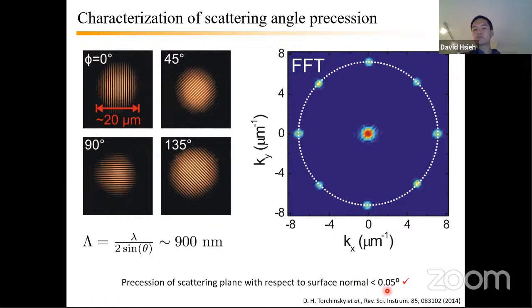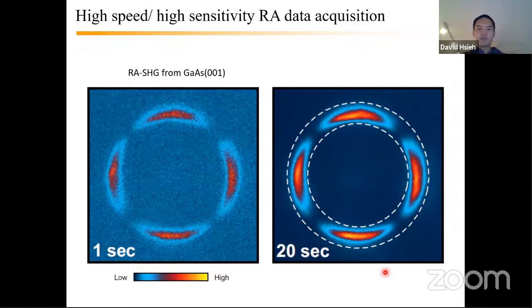It's limited to less than about a 20th of a degree. So all these improvements to the setup enable us to take, I think, pretty good RA SHG data on challenging samples in extreme environments. As I mentioned, the types of data I'll be showing look like images like this, okay? And so the intensity, this is the second harmonic reflection, and going around the circle is different scattering plane angles.